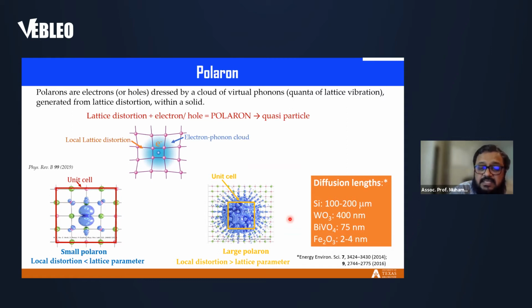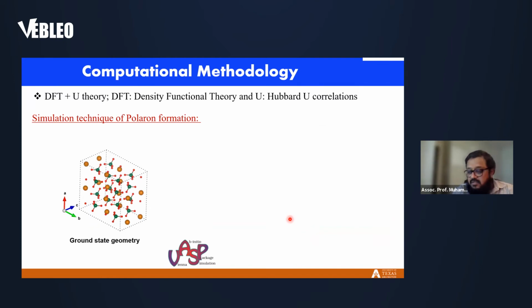The transport is deteriorated. Now, computational methodology, what we did, we used density functional theory. We know that density functional theory by itself, with standard approximations, underestimates electron localization or electronic correlation. Hence, we use DFT plus U, where U is the Hubbard electron correlation parameter. It's a tradition to say parameter, but nowadays we can calculate it from first principle methods as well.